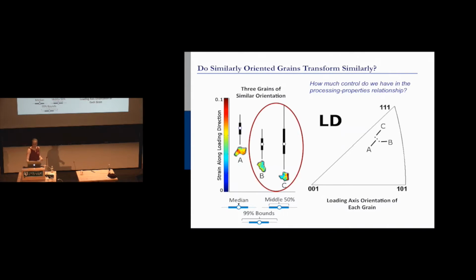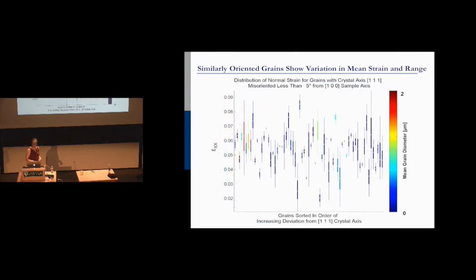So what happens if we take, let's say, all the grains in the field of view, each one containing about 5,000 strain data points, and we just plot ones that are less than 5 degrees misoriented from each other. So we picked the sample axis just to have a reference point. And any grain that was oriented less than 5 degrees from the sample axis, we plotted. Where the thick part is the 50% of those 5,000 data points that fall in that strain. The thin part is 99%. And the color is how big the grain is, because maybe the size of the grain matters. And it turns out, it's all over the map.